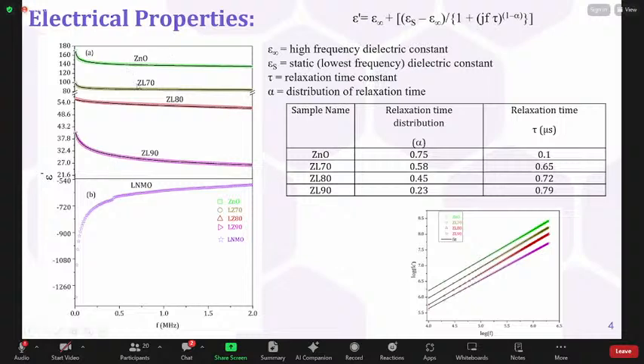But as the LNMO part increases, the dielectric constant decreases, because we know that LNMO is conductive in nature due to the Zener double exchange between Mn+3 and Mn+4. That's why as we increase the content of LNMO, the composite shows a decrease in dielectric nature, and LNMO shows a negative dielectric constant, which shows LNMO has a purely conductive nature.